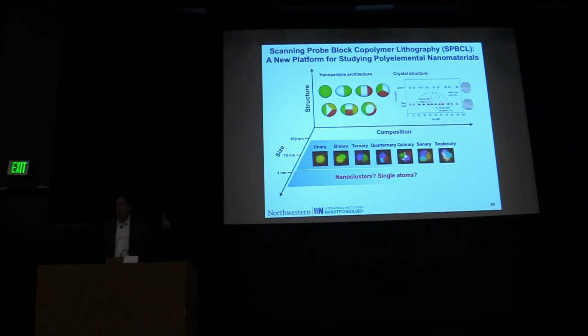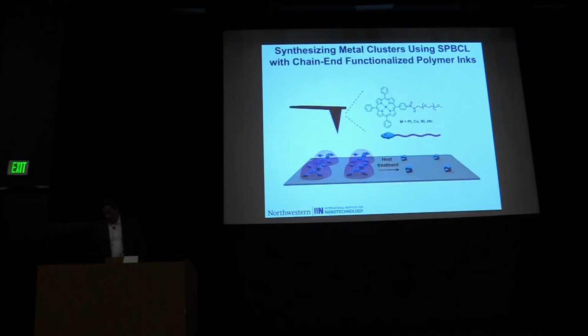So I said, in principle, we should be able to go down to a single atom. We should be able to reduce the number of metal atoms, and then ultimately get an atom and know where that atom is, and 2 atoms, and 3 atoms, and 4 atoms, and 5 atoms. Well, it's a little more difficult than it sounds, because as you start diluting, you run into a big sampling problem, right? And so you get a stochastic mess. So again, these guys figured out that what we could do is effectively synthesize polymers and use end capping now to make the reactor effectively primarily polymer and reduce the number of metal content in a highly controllable way.